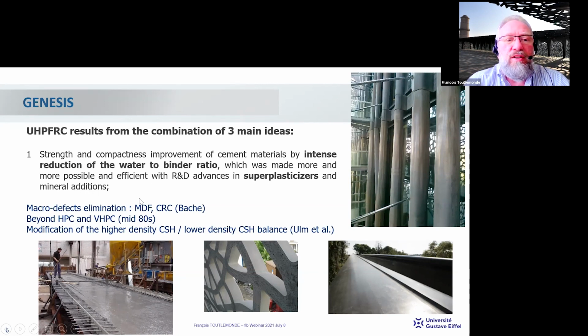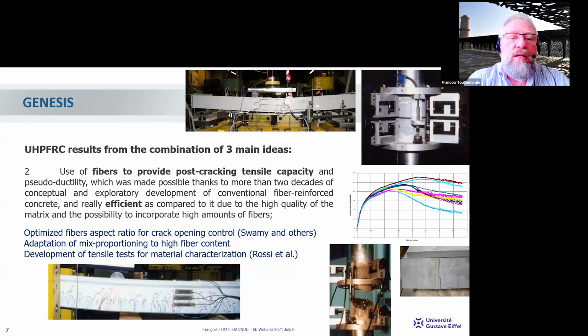This reduction in the water to binder ratio leads to modifications in the ratio between high density CSH and low density CSH. So this low water to binder ratio modified the balance between the hydrates in the cement paste. The second main idea, of course, is the fibers.